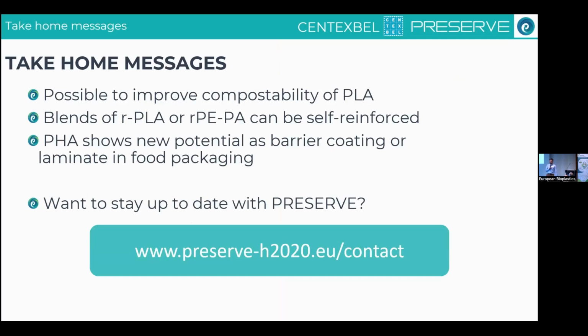So finally, some take-home messages. First of all, as I mentioned, it's possible to improve the compostability of PLA using these enzymated master batches. It's also possible to self-reinforce blends of recycled PLA or blends of recycled PE with polyamide to improve their properties. PHA also shows quite new and interesting potential as a barrier coating for food packaging, but it's something we will still have to work on to really get it market ready.